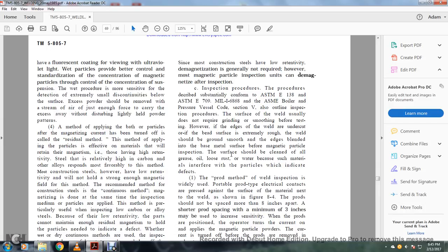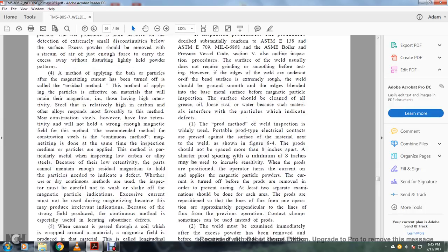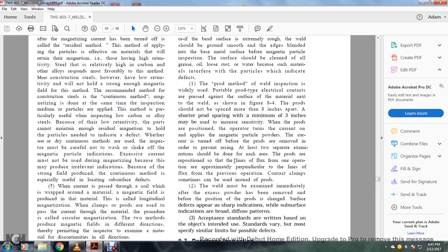Magnetic particle inspection. The surface should be cleaned of all grease, oil, loose rust, and water, because these materials interfere with the particles indicating the defects. 1. The prod method. In welding inspection, widely used portable prod-type electrical contacts are pressed against the surface of the material next to the weld, as shown in Figure 8.4. The prods should not be spaced more than 8 inches apart. Short prod spacing, with a minimum of 3 inches, may be used to increase sensitivity.